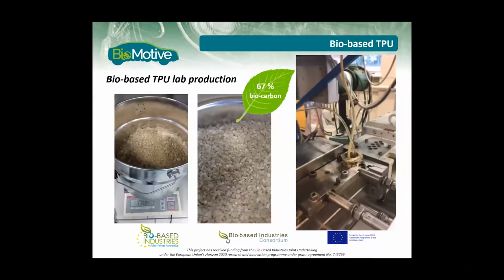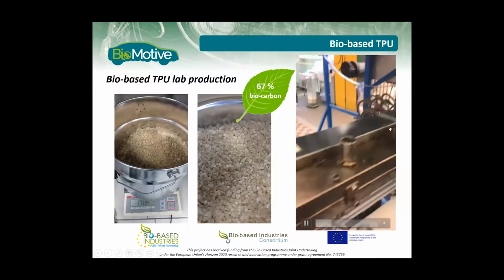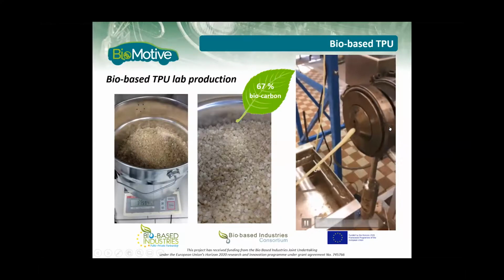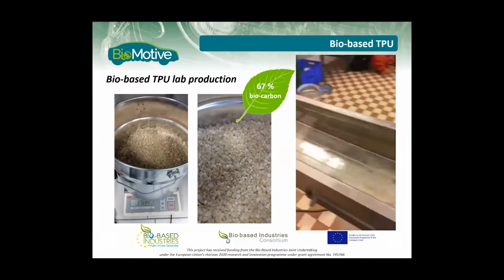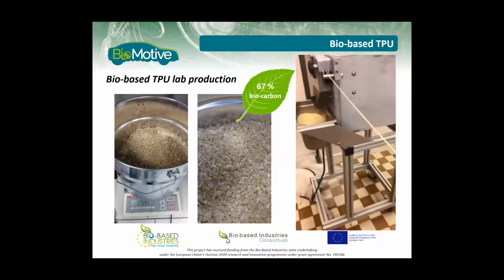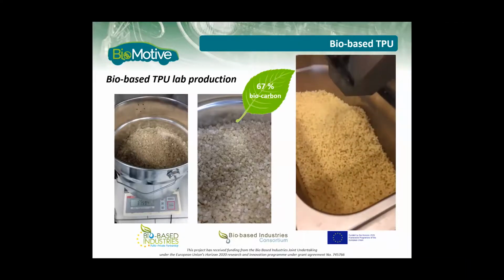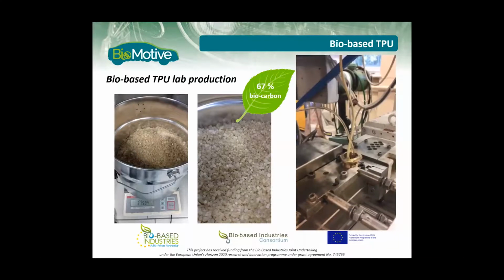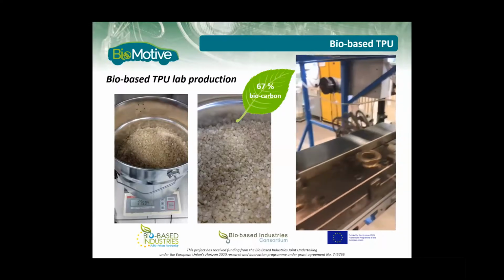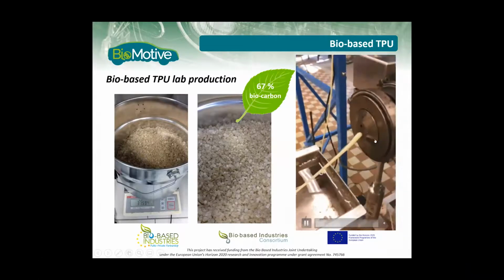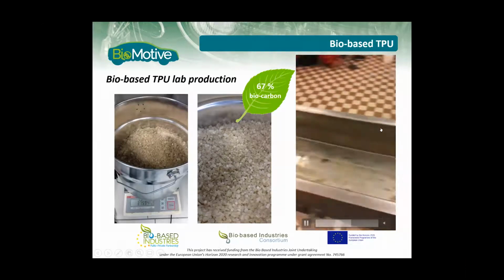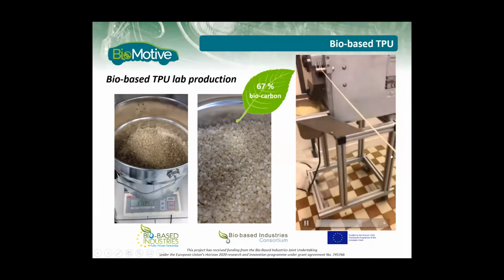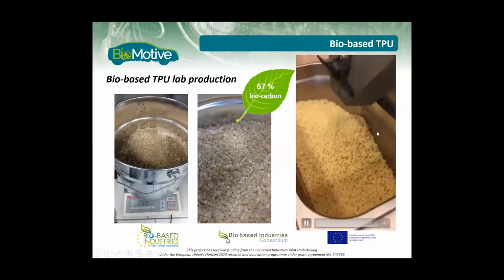As for the TPU, on the right side on the video, you see two components of the TPU, thermoplastic urethane, being fed into the extruder. The extruder has two screws inside that are mixing those two components, allowing the reaction to happen. And after 1 meter in the extruder, you can already see a wire that is already a reacted plastic, polyurethane.